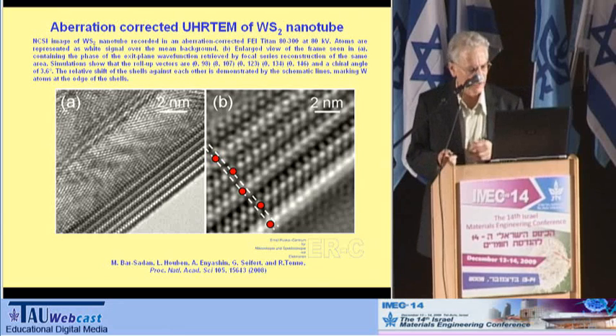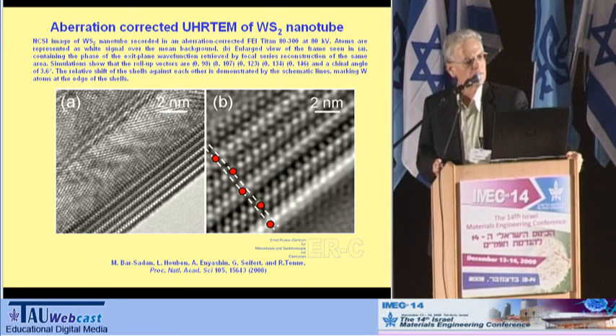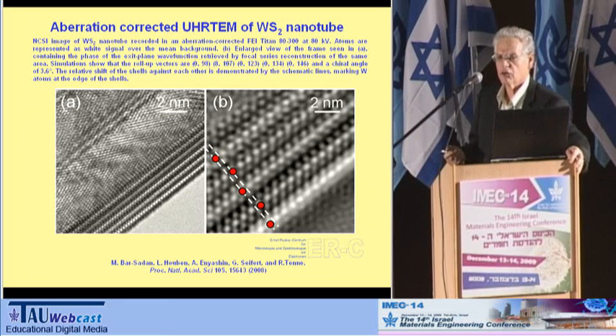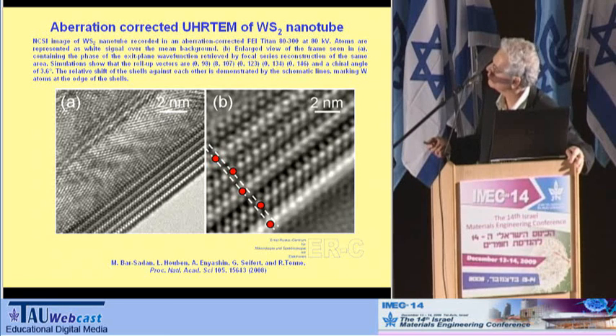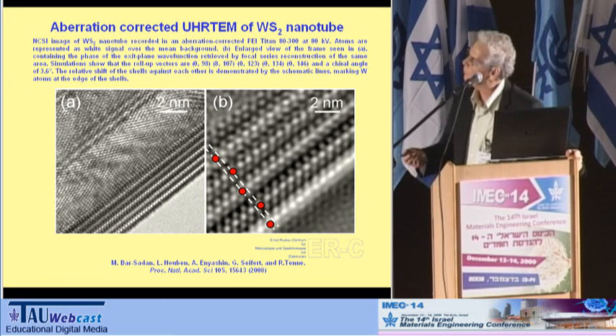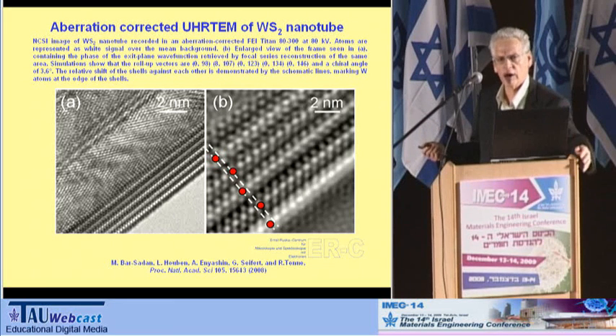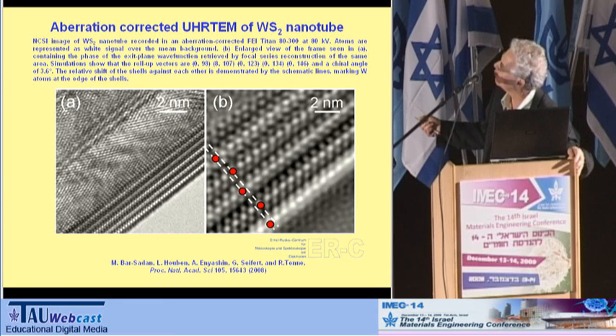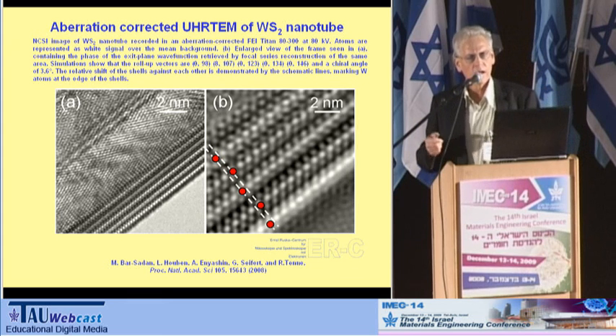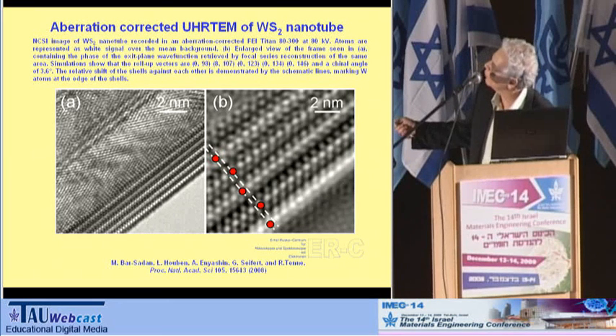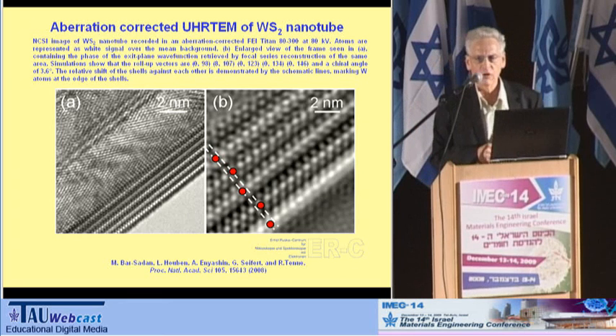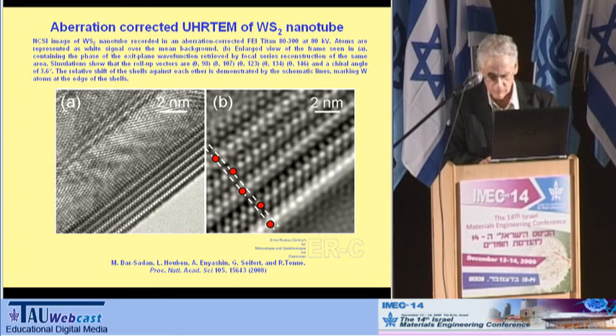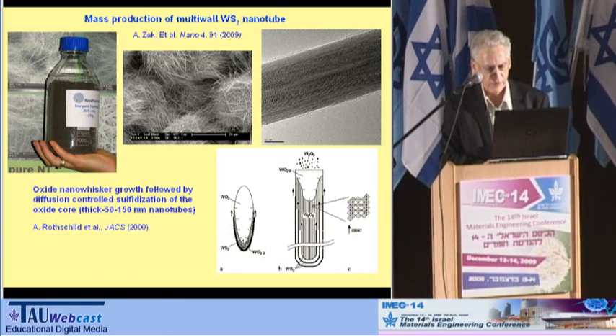This is actually a study that we have published jointly with Dr. Maya Bar-Sadan, who is in the audience or might be in the audience. She finished her postdoc in Jülich in the laboratory of Knut Urban, who is the plenary speaker tomorrow. And using the CS-corrected, aberration-corrected microscope, you can see now the detailed structure of the nanotubes. You can see the atoms, the well-arranged tungsten and sulfur atoms. She has been able to calculate the structure, the chirality of each wall among these multi-wall nanotubes and infer the growth mechanism of these nanotubes in a very exquisite and precise way. And this is a tremendous advantage of using such a high-resolution electron microscope to unravel the growth mechanism of nanoparticles.